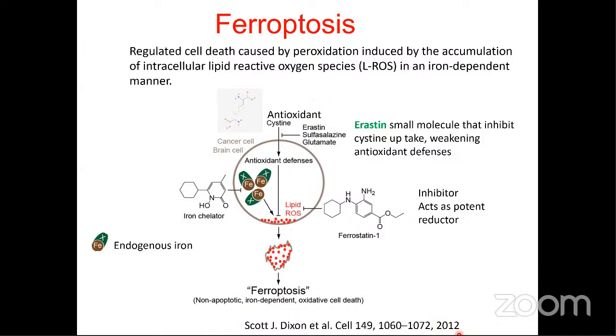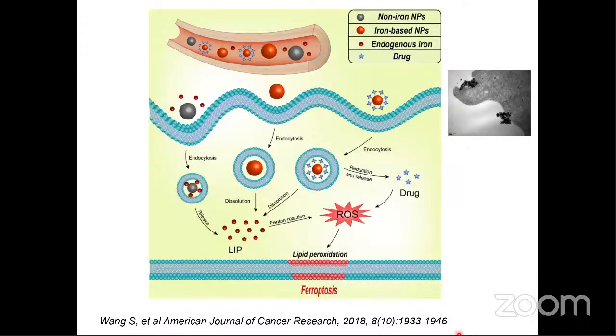And later, it has been proposed that iron-based nanoparticles can participate in this process: once the nanoparticle is endocytosed, it goes through dissolution, and from dissolution to Fenton reaction, from Fenton reaction to ROS, and then lipid peroxidation, and the nanoparticle can also produce ferroptosis as a new form of inducing death in the cells.